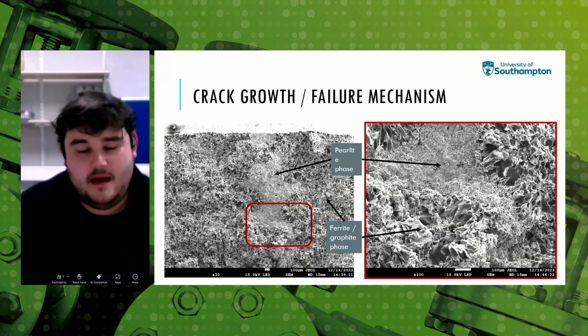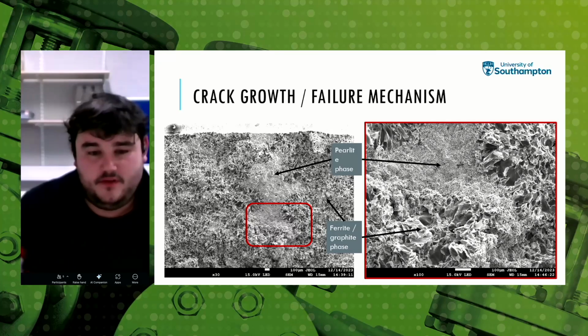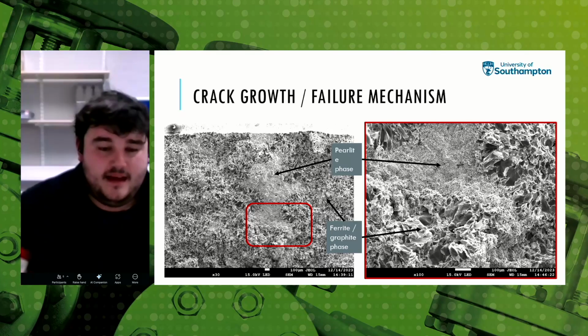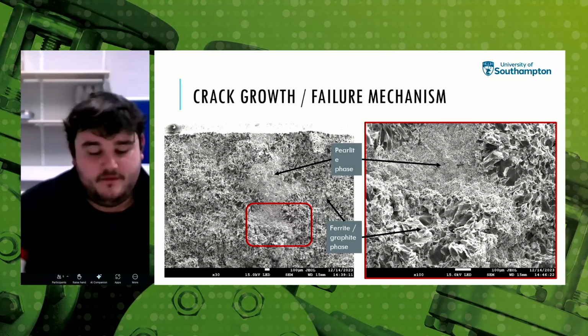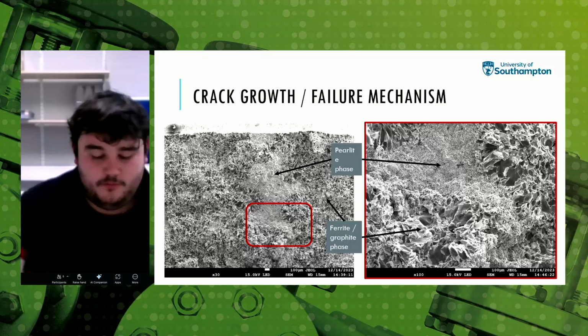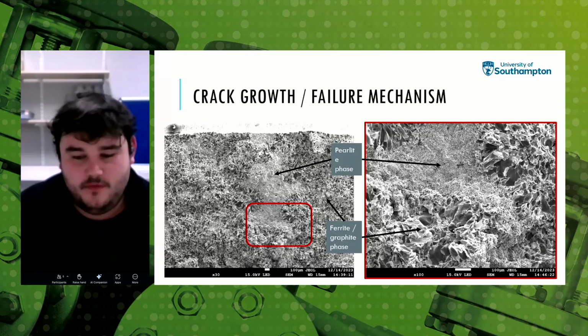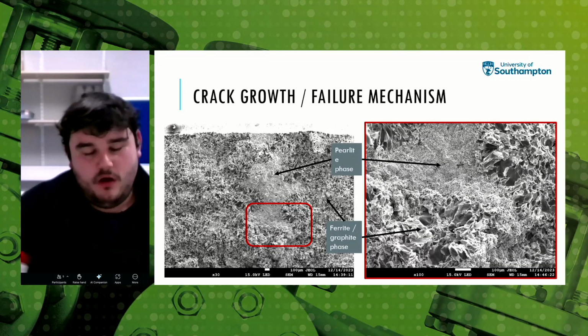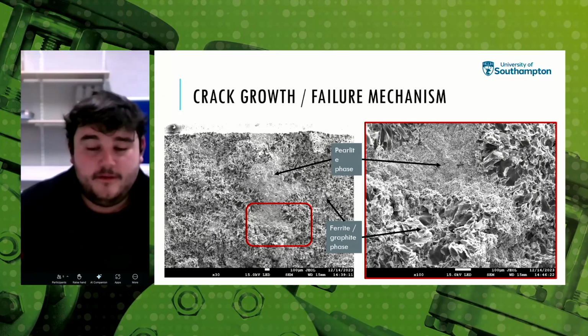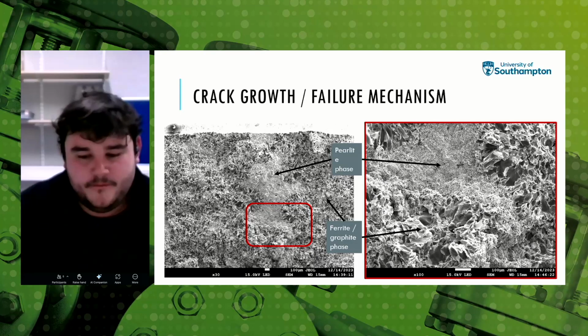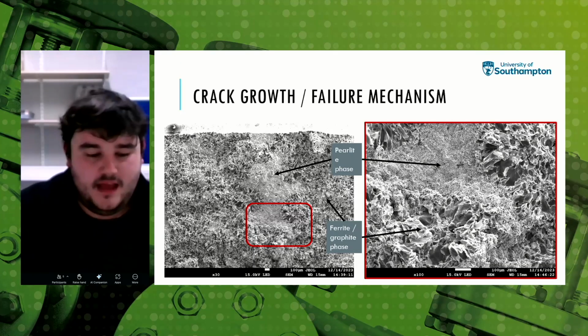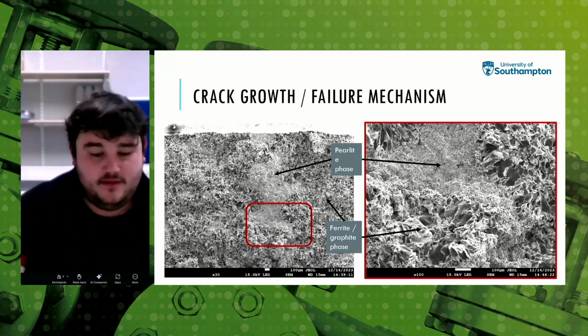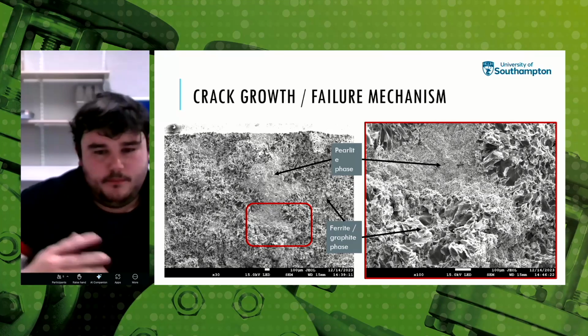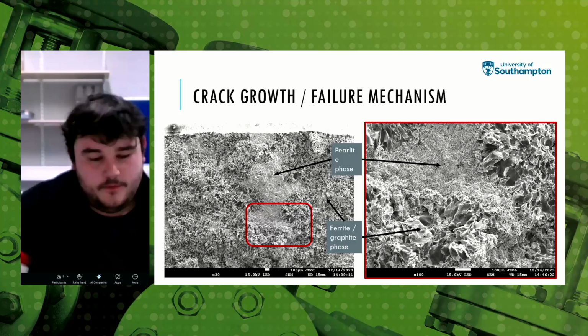So here is an SEM image of one of those fractured surfaces. And you can see there's smoother regions and there's quite blocky regions. Basically, the ferrite graphite fails in a very brittle manner. This is often of little mechanical support to the material, whereas those pearlite regions fail in a much more ductile manner. So it can be said that that is what's actually holding together the material. It's a network of these pearlite phases interdispersed with the ferrite graphite layers running through.